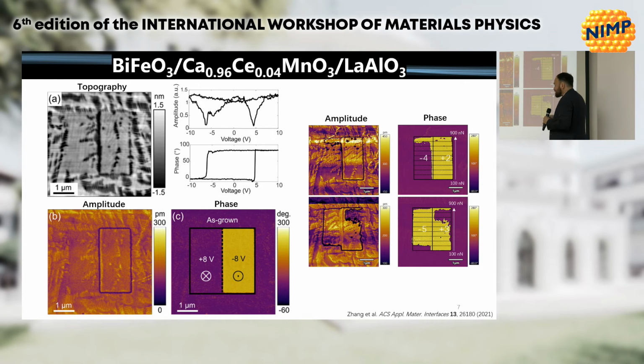Okay, so to illustrate the point here that the applied force can influence the switching, what we did again was start with this minus 8 and plus 8 and minus 8 switching. You can see the amplitude here. And then we started applying both a switching voltage, so in this case minus 4, which normally wasn't enough to switch the material, and we did it as a function of force. So while scanning, we start down here, we apply 100 nanonewtons. As we're scanning, we're increasing the force. And the minus 4 volts that usually didn't switch the material now switches it when we get up to 800, 900 nanonewtons. Similarly, on the other side, starting with minus 8 volts and applying a positive 2 volts, which normally wouldn't switch, we can go all the way up to 900 nanonewtons and it doesn't switch.